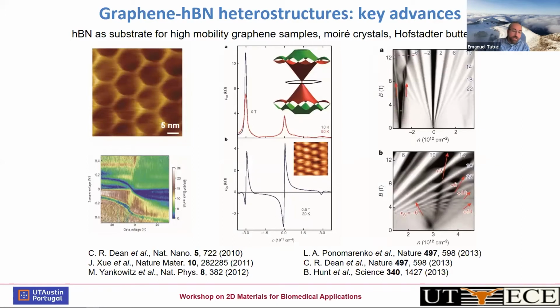I should say historically that ever since graphene was exfoliated down to the monolayer, not long after people managed to exfoliate other materials. Transition metal dichalcogenides came before the hexagonal boron nitride. And not too long after, people started to wonder, okay, now we've gone down to the monolayer, can we now build structures that combine these materials in a way that departs from what we would see in natural crystals, and also perhaps with different properties that can be engineered in these types of structures. And the heterostructures that arguably elevated the field in the early 2010s and shortly thereafter are the hexagonal boron nitride graphene heterojunctions, or graphene encapsulated in hexagonal boron nitride. And that's because hexagonal boron nitride, just like graphene, is atomically flat. It has a very low concentration of defects, and doesn't have charge defects like other dielectrics, for instance, silicon dioxide.